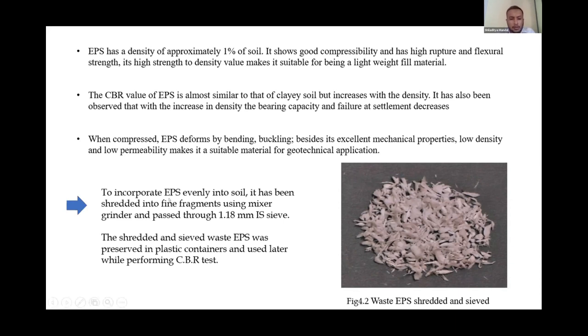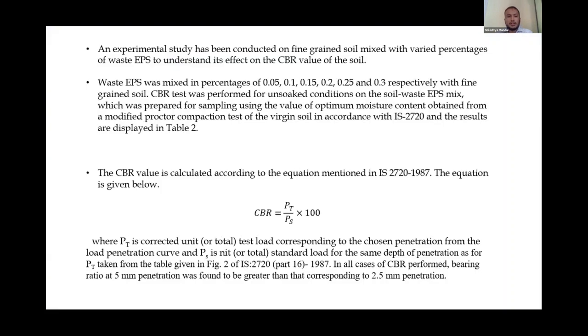So EPS was incorporated evenly into the soil. It was mixed with hand mixing techniques, and it was made sure that it is thoroughly mixed with the entire soil sample during the sample preparation. So coming to the results and discussions. An experimental study has been conducted on the fine grain soil mixed with varied percentages of waste EPS to understand its effect on the CBR value of the soil. And these were the percentages up to which we have tested our soil with the CBR. The most important thing is we have performed tests for just unsoaked conditions on the soil waste EPS mix.